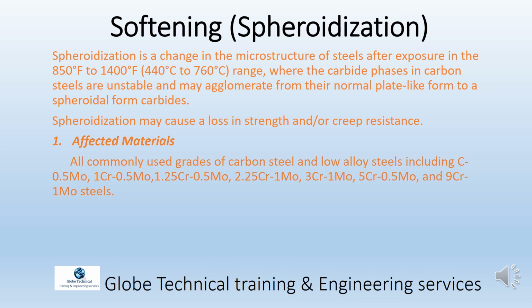Spheroidization is a change in the microstructure of steels after exposure in the 850 degrees Fahrenheit to 1400 degrees Fahrenheit, 440 degrees Celsius to 760 degrees Celsius, range, where the carbide phases in carbon steels are unstable and may agglomerate from their normal plate-like form to a spheroidal form carbides. Spheroidization may cause a loss in strength and/or creep resistance.